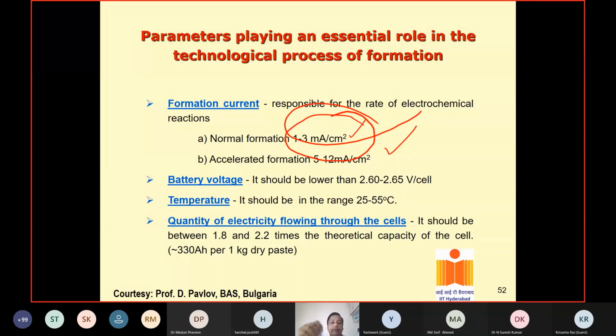Again, when you do charging, the voltage should be kept at a maximum of 2.6 volt per cell. And the temperature, as I told you, should be maintained between 25 to 55 degrees centigrade. So these are the important parameters. The current, voltage, and temperature are three important parameters that help us make better batteries.